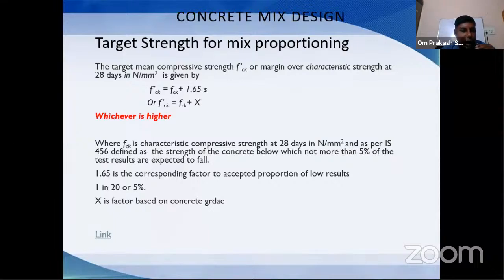fck bar equals fck plus 1.65s. So fck is our 25 if we are talking about M25, plus 1.65s. It's a factor which corresponds to 1 in 20 or 5%. What is this? Actually, 1.65 is a factor which is considered against the 5% failure. It means if we are testing or checking 100 samples for the M25 grade, as we are designing here, not more than 5% of results should fall below 25.